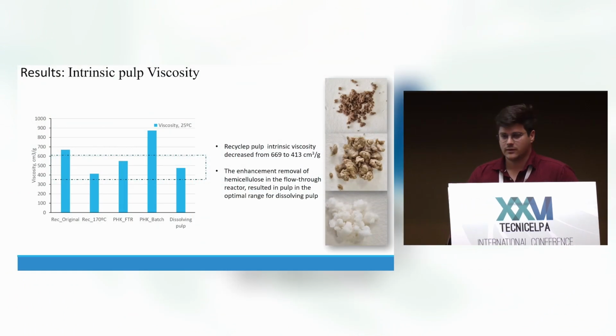Regarding intrinsic viscosity, we can see that the treatment employed in the recycled pulp decreased the value to pulps with a better quality, aiming for dissolving pulp, so between 350 to 600. And the prehydrolysis kraft with the flow-through reactor also reduced the intrinsic viscosity to the optimum values to produce dissolving pulp.